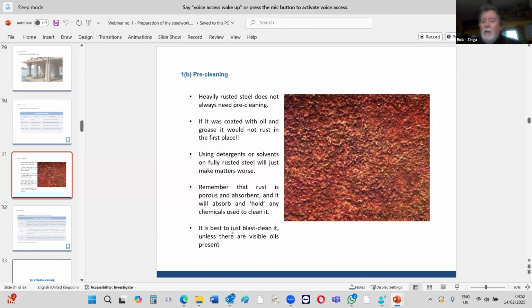What I was saying earlier with ExxonMobil in Malaysia, they have this rust. And they said we have many areas that are going to be blast cleaned in 5 years' time. That's our shutdown. It's planned, it's budgeted. So every few years we have these major shutdowns for 2 weeks. He says, but the rust cannot advance and get more pitting or whatever. And that's why we designed the frontline maintenance on that sort of surface. So that surface you see is an orangey sort of color. So that would be removed with a wire brush, de-dusted with a clean paint brush, so it's all nice and clean. And then you put aerosols. So you put maybe 3 or 4 passes, maybe more.